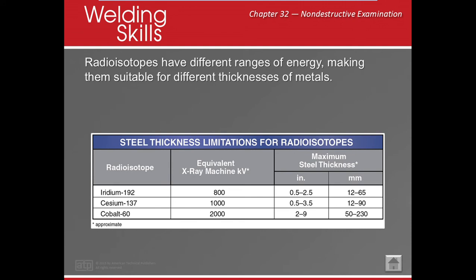Radioisotopes, or gamma ray sources, are a different type of radiation source. Common types include Iridium-192, Cesium-137, and Cobalt-60. There is no on/off switch — the source is shielded in lead, and when needed, it is reeled out to the required position and the radiation exposes the film. Cobalt-60 can penetrate between two and nine inches of material. The major advantage of radioisotopes is portability — no electricity is needed — but the downside is you cannot turn them off.